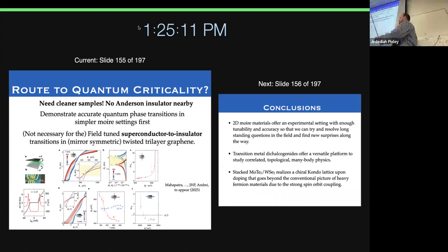So out-of-plane field, you feel the disorder strongly because of your big magnetic loops. So you're going to be dominated by Griffiths physics. The prediction would then be that z, the dynamic exponent, goes to infinity at the transition, which they see beautifully. You apply an in-plane field. This should be a superfluid insulator transition. Nu z should be about 4/3. I put that dashed line, I don't know if it's that accurate, but anyways, yeah, I think that is reasonable.